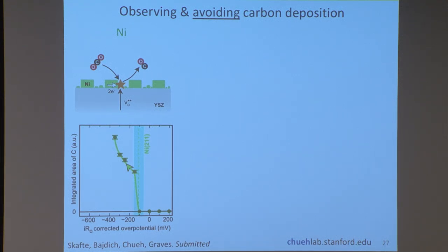The first example is showing you the catalyst that is good for both. Okay, this is nickel. And you're able to make a lot of carbon, which is what's shown in the y-axis here. And you can do this at the equilibrium potential. So this is the thermodynamic expectation. That's the blue box there. So right at the expected potential, carbon shows up. And we see this using the operando experiment I mentioned. So this is no surprise. Nickel is very good for both.